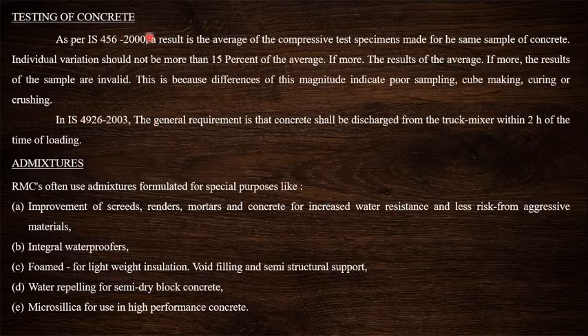Testing of concrete as per IS 456: a result is the average of the compressive strength specimens made from the same sample of concrete. Individual variation should not be more than 15% of the average. If more, the results of the sample are invalid. This is because differences of this magnitude indicate poor sampling, cube making, curing and crushing.